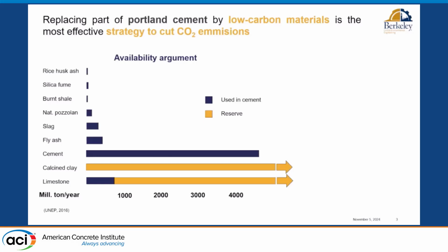So replacing part of the cement, which is equivalent to reducing the clinker factor, is the most effective way that we have to tackle the CO2 problem of the concrete industry, at least fast, on a short time scale. And why do we go for limestone and calcined clays? Because they are very abundant as compared to the demand of cement that we have right now. None of the other SCMs, even combined, can reach quantities and availabilities that can compare, for example, with a 50% replacement of that quantity of cement.